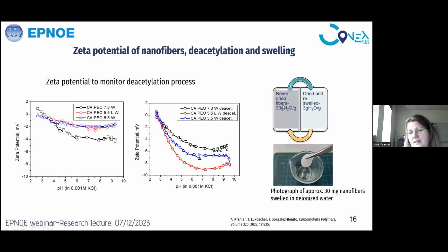And here you can see that if we talk about never-dried fibers, their water absorption capacity is 33 grams of water per gram of fiber. Here you can see the photograph of approximately 30 milligrams of nanofibers that are swelled in deionized water, and they are not dispersed in water. They completely retain the shape. Unfortunately, if you dry this material and reswell it, we are reducing the absorption capacity, but it's still quite high. It can absorb 3 grams of water per gram of material.